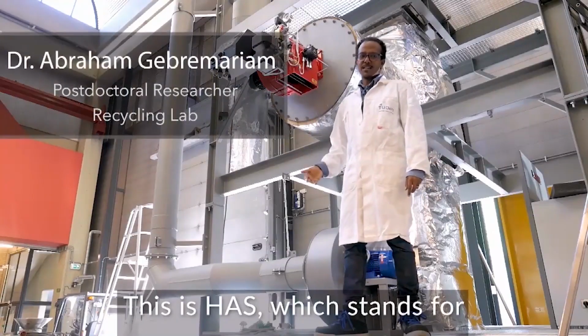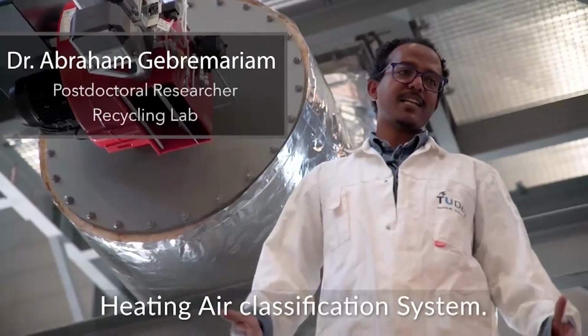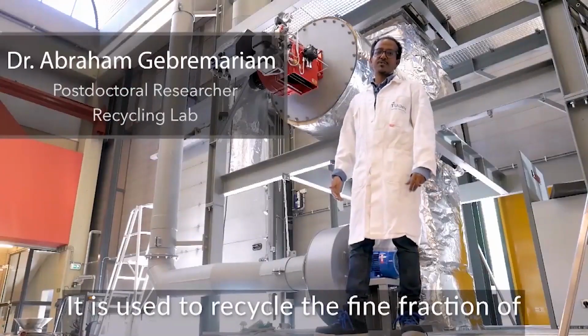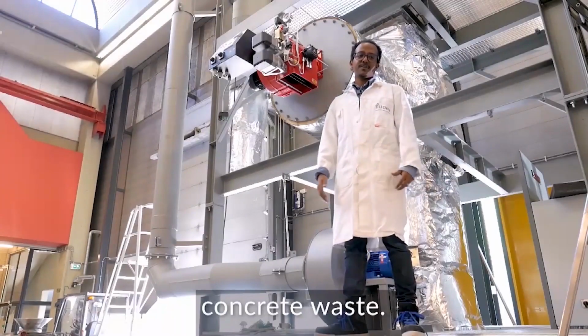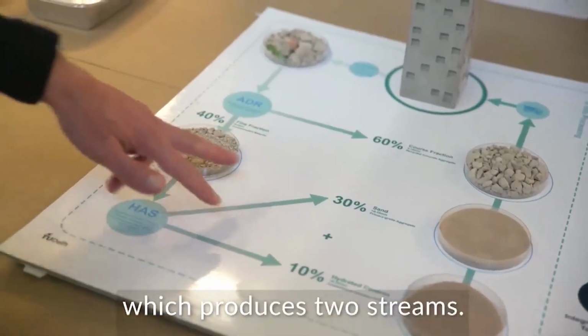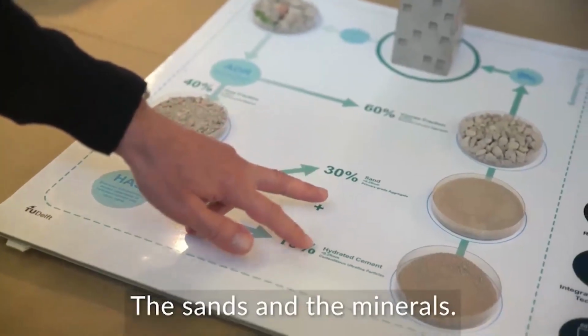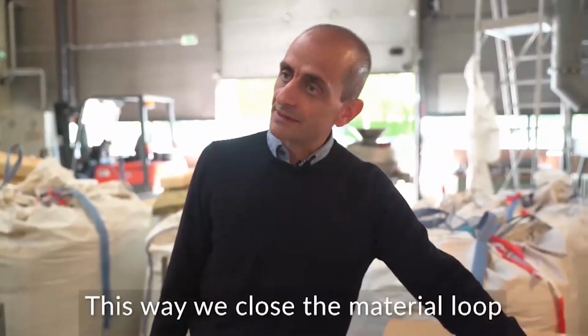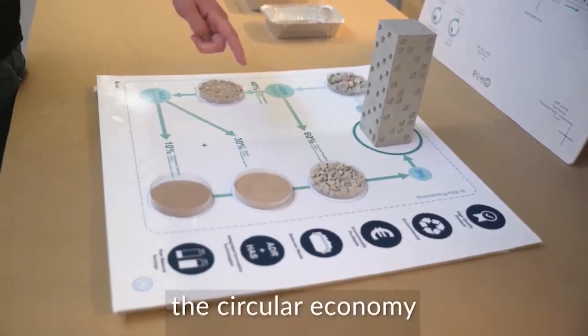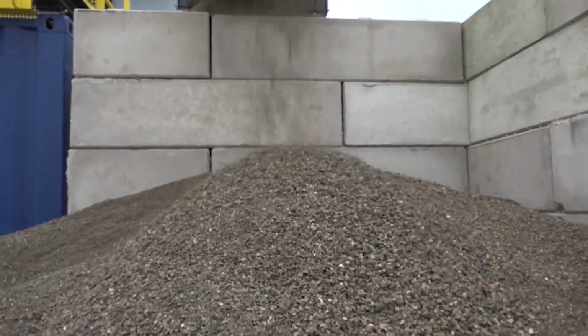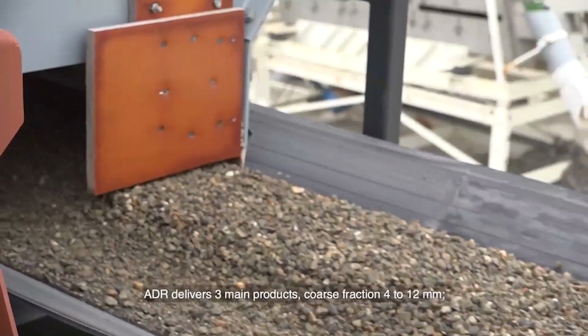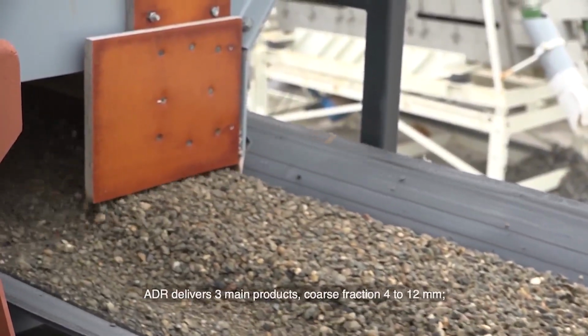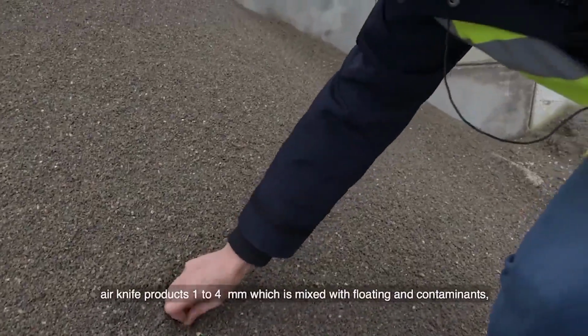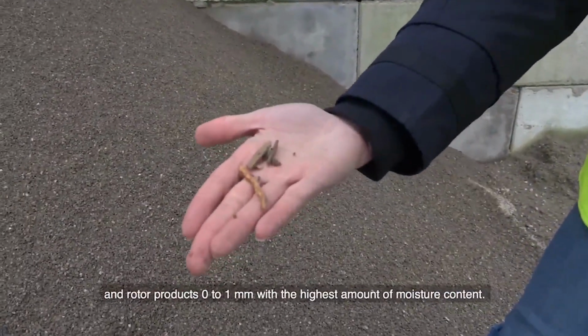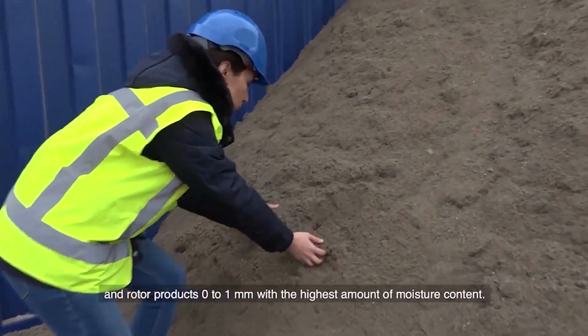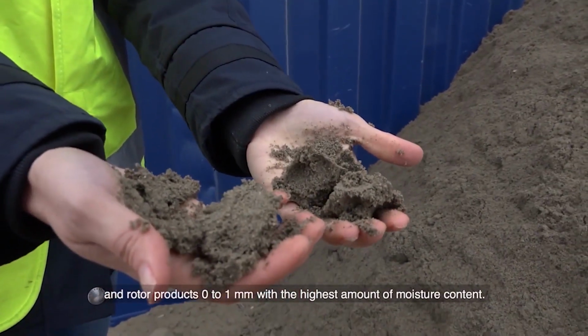This is HAS, which stands for Heating Air Classification System. It is used to recycle the fine fraction of concrete wastes, which produces two streams, the sands and the minerals. This way, we close the material loop and we effectively implement the circular economy in the construction sector. ADR delivers three main products: coarse fraction 4 to 12 mm, air knife products 1 to 4 mm, which is mixed with floating and contaminants, and rotor products 0 to 1 mm with the highest amount of moisture content.